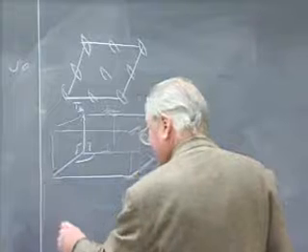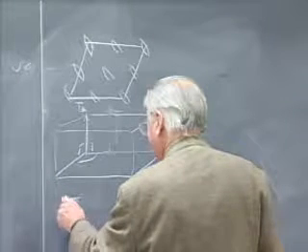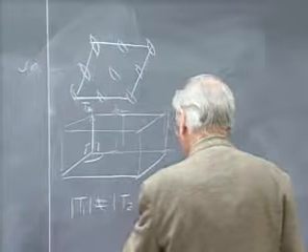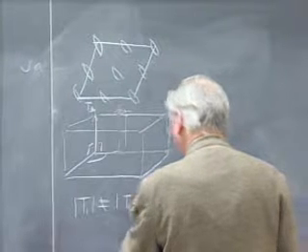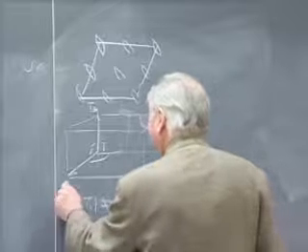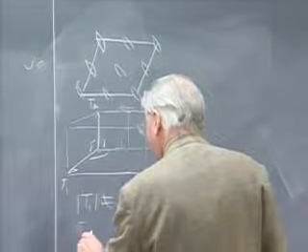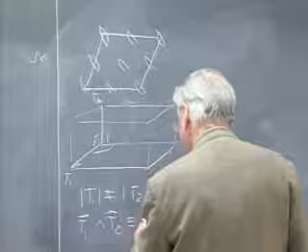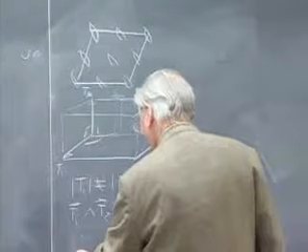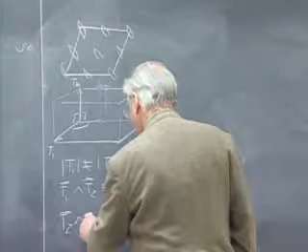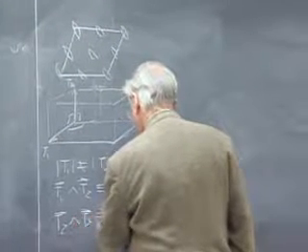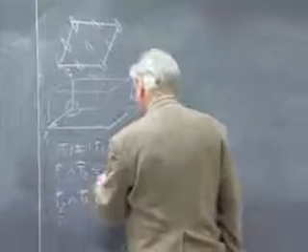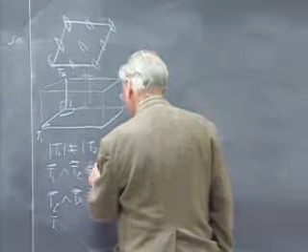Okay, so here we have a degree of specialization. The translations remain unequal in magnitude. They can be any length they wish and not change things. But two of the interaxial angles, T1 to T3, is identically 90 degrees. The angle between T2 and T3 is identically 90 degrees. And the third angle, the angle between T1 and T2, is my general angle. So this can be anything.